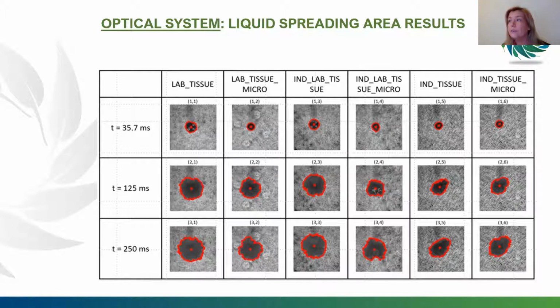And finally, the last two columns are for the industrial tissue samples. Both have been creped and they have the same mixture of eucalyptus and softwood. In column 5, the sample is without embossing, and in the last column, the same sample with the embossing pattern. The paper structure and anisotropy effect resulting from the creping operation is visible in the last two columns of this image, where we are obtaining an elliptical shape.